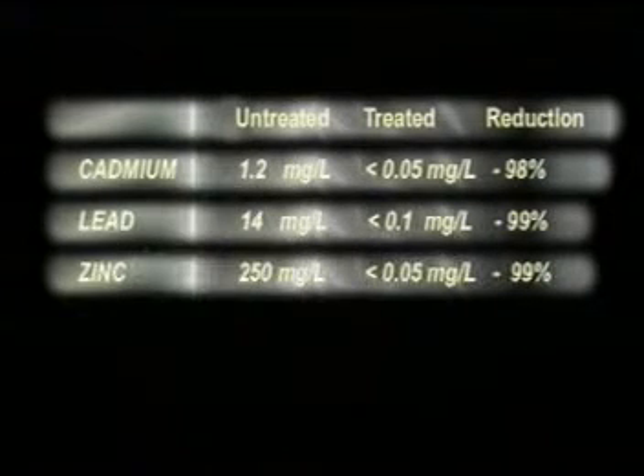Prior to stabilization, zinc was measured at 250 milligrams per liter. Post-stabilization levels were less than 0.05 milligrams per liter. A 99% reduction of leachable zinc was achieved.